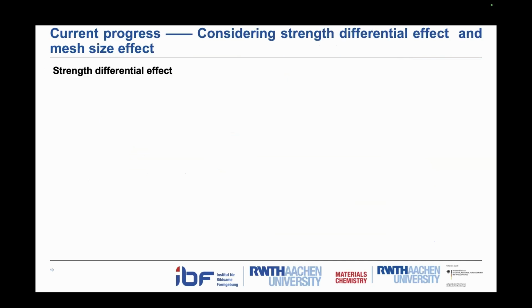So following the routine, first of all, we still need to consider one very important thing, which is the strength differential effect, which refers to the asymmetric response to the external loading on the tension side and the compression side, and exists widely in HCP structured metals, and zirconium belongs to HCP structured metals. And also during 3-point bending, tension and compression exist simultaneously. So it reminds us that when we run the simulations, we have to couple this strength differential effect into the simulations.